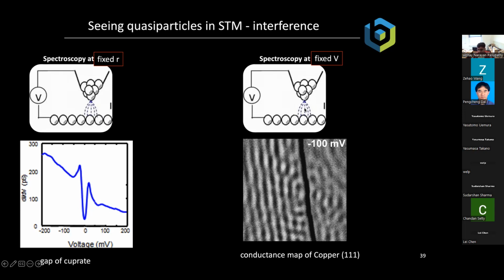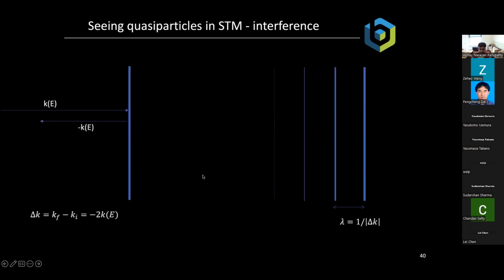And you would see, for example, the superconducting gap if this is a high TC superconductor. The other kind of measurement is we can pick a particular voltage difference, or a particular energy of the tunneling quasiparticle, and we can measure at that particular energy what the density of states looks like in space. And this is a very simple material, copper 111. If you look at copper 111 and you measure the density of states at some particular energy, you'll see this is a step edge in copper 111, but you'll see these beautiful wave-like fringes near the edges of the step. And this is nothing but interference.